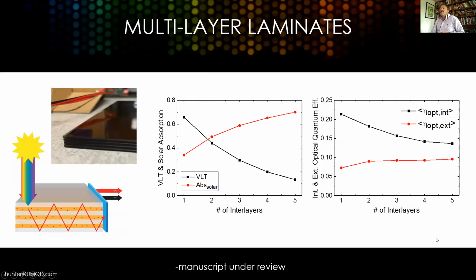Another approach to optimizing the aesthetics is to think about the visible light transmission, basically a darker tint or a lighter tint. Architects want to be able to adjust that. By adding more dots to the single layer, you can run into solubility issues. The dots can start to crash out in the polymer, and you get a hazy waveguide, which is not very effective for generating electricity.